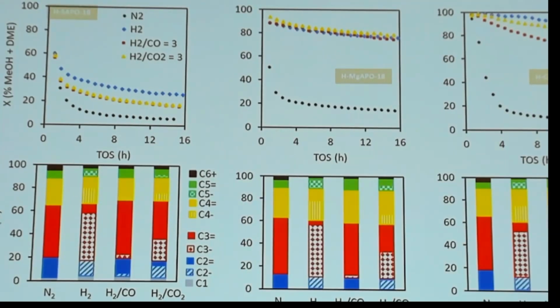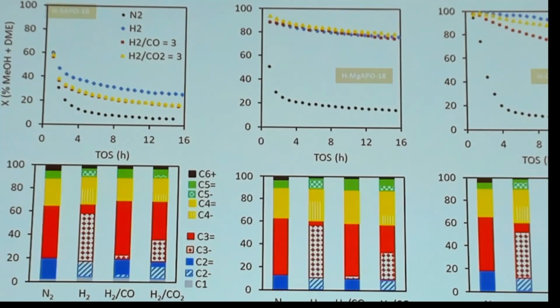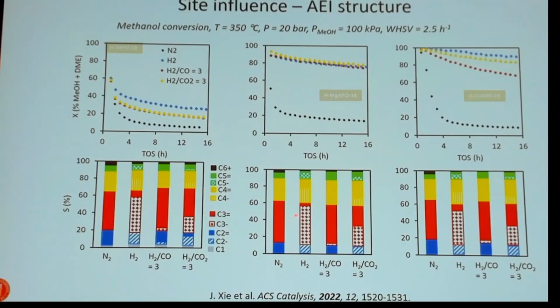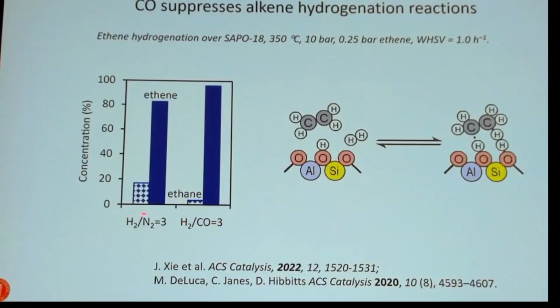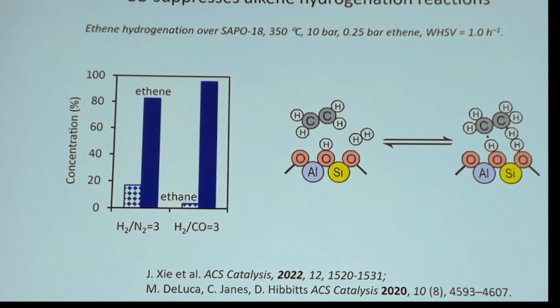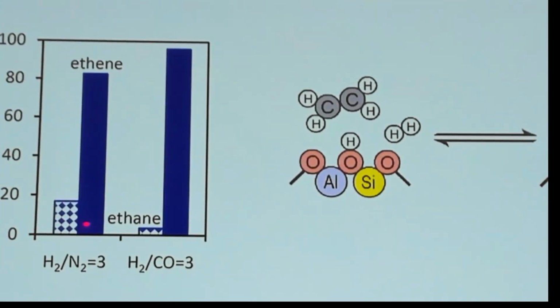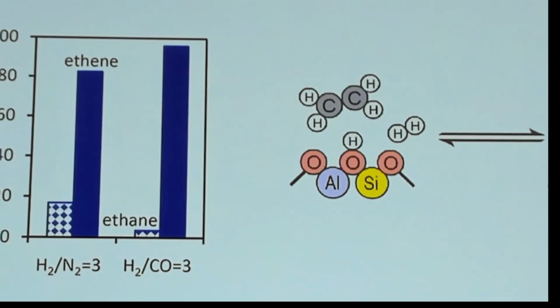For the other two variants, the magnesium and cobalt variants, we see that it is exactly the same. CO co-feed is suppressing the hydrogenation of the olefins, while it is maintaining the olefin selectivity. We wanted to confirm that it was really a suppression of the hydrogenation reactions that we could see. We did this by feeding either hydrogen in nitrogen or hydrogen in CO over the same stable catalyst. And we see that the amount of ethane being formed is much lower when we have CO present.